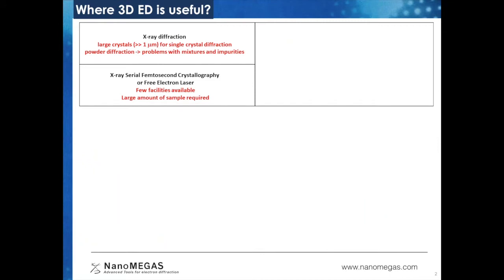Now, there are different methods for extracting structural information from a crystalline material. The most common method is X-ray diffraction, but with single crystal X-ray diffraction, one needs at least a 1 micrometer crystal or larger. For powder diffraction, though the crystal size requirement is small, if there is more than one phase present in the material, extracting the structural information is extremely challenging. Another possible method to extract structural information is X-ray femtosecond crystallography or free electron laser. But each of these methods has its own challenges.